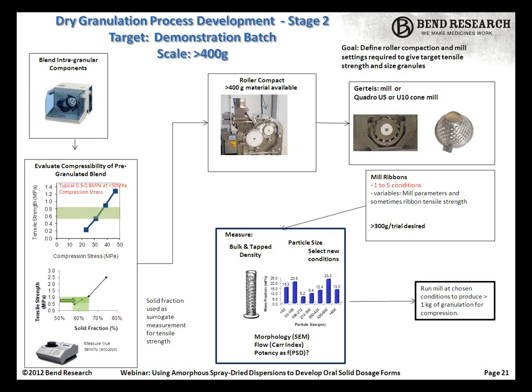So that is a little less predictive, so we end up doing anywhere from 1 to 5 conditions typically to achieve a range of granule sizes that we then will evaluate for tableting in some cases, and more often than not, we'll take those at small scale to assess whether there's an impact on our dissolution performance and compressibility.